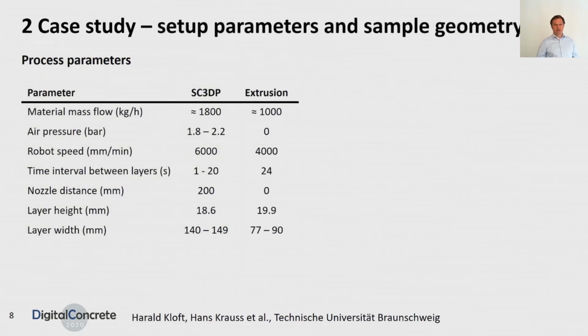Now, the process parameters we used are of course different for the two processes, because we found different optimum parameter ranges for the two processes in order to get proper specimens. In the case of material spraying, we could manage a higher material mass flow and also a higher robot speed without fracture of the strands in the fresh state. And of course, we used an air pressure of about 2 bars and a nozzle distance in the case of shotcrete 3D printing, whereas in the case of extrusion, we attach the extruder head to the substrate layer.